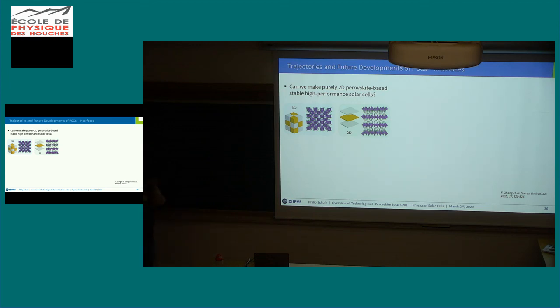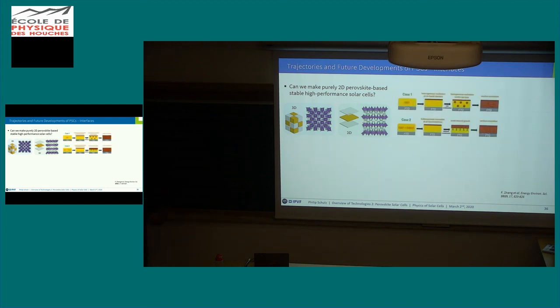If you have a layered film with these essentially carrier blocking organic molecules that are intercalated, you can't transport the charges that you generate. So what was key here is to adapt your production procedure and grow from the top these columnar structures, where you now have a 3D channel from the top to the bottom that is separated by 2D walls, so to say. And with this, you can make these complex cells.